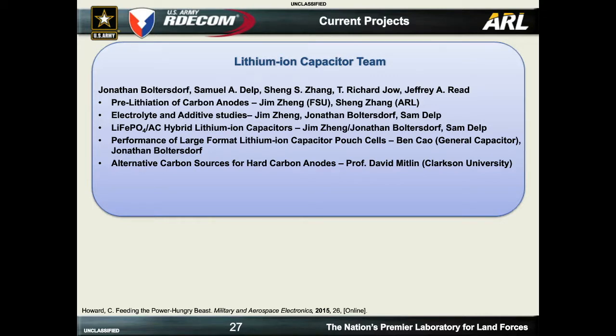One of the things that's very important in lithium-ion capacitors is that because you put in a very heavy anode, you have to pre-lithiate the anode. There's no way around that, really. So unlike a lithium-ion battery where you build the cell in a balanced format, in a lithium-ion capacitor you really need to pre-lithiate it. The problem with that, of course, is that it adds a significant cost to the process, and also it's not necessarily that uniform the way that it's done. So I'll talk a little bit about some of the work we've done there, and then a little bit about electrolyte and additives for lithium-ion capacitors, trying to improve the high-temperature performance of these systems.